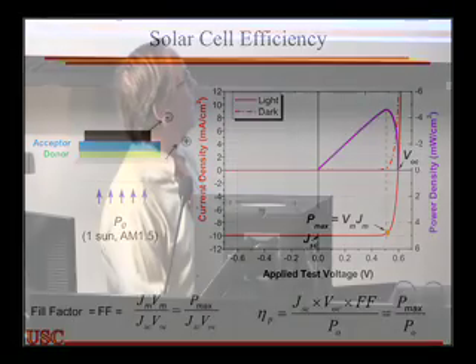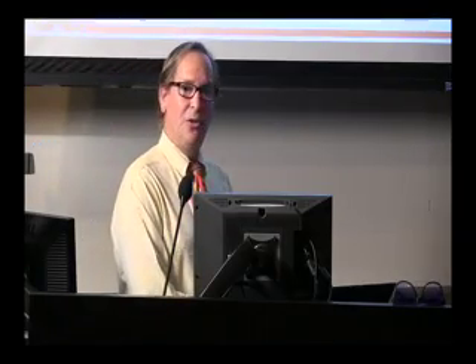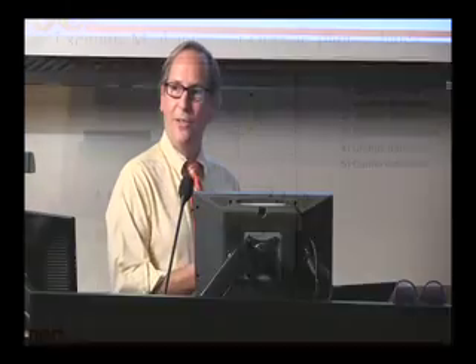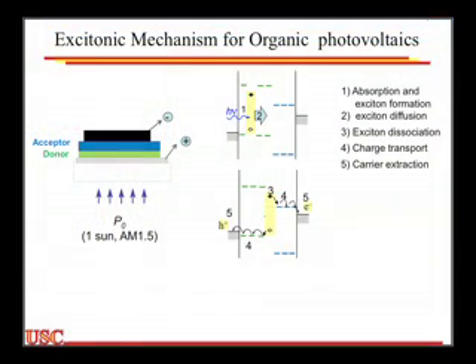So how does a solar cell work? It's a little different than a silicon solar cell or a gallium arsenide or a cadmium telluride. In organic materials, the exciton has a relatively high binding energy, somewhere between 300 millivolts and maybe even upwards of 1 volt binding energy for that exciton. What that means is, in contrast to inorganic semiconductors, where the exciton itself is not bound, and at room temperature it spontaneously makes the hole and the electron, we have to go to an interface.